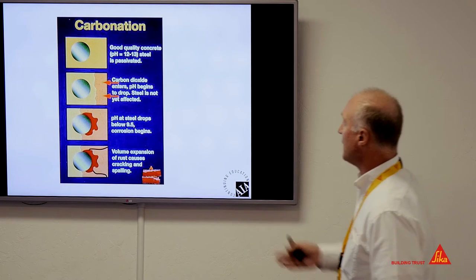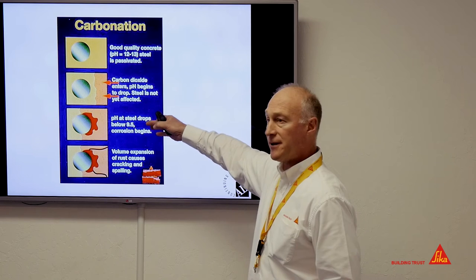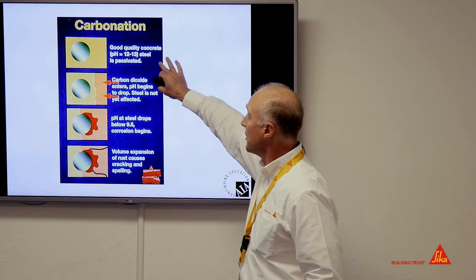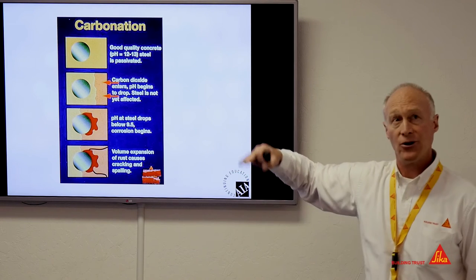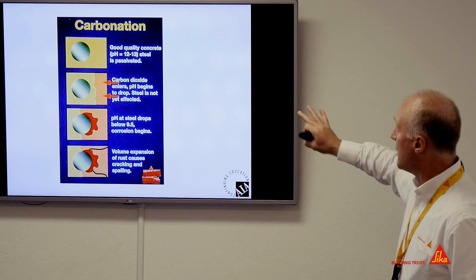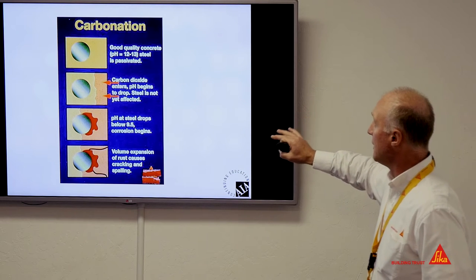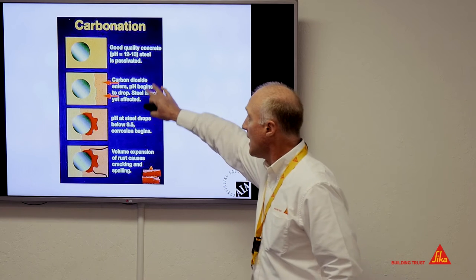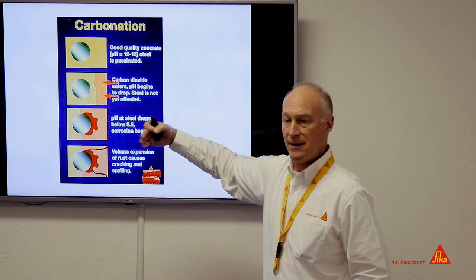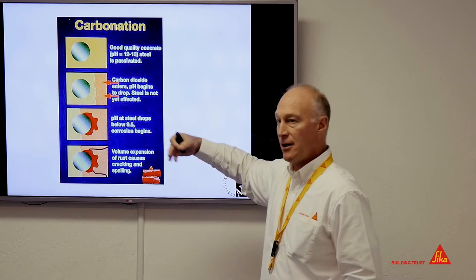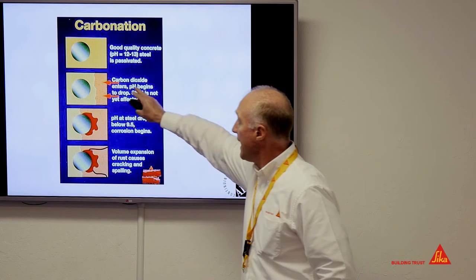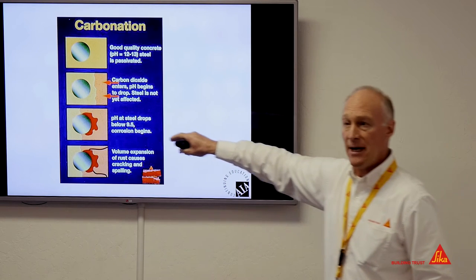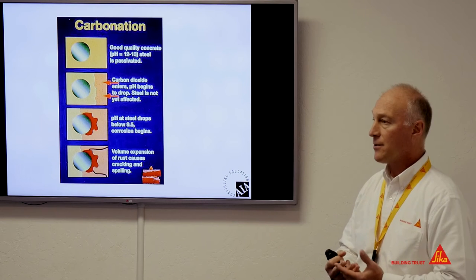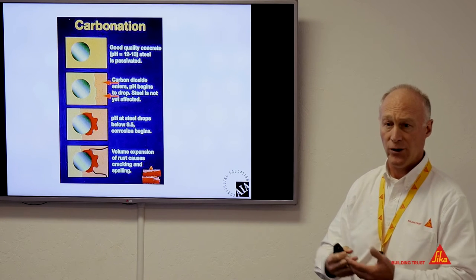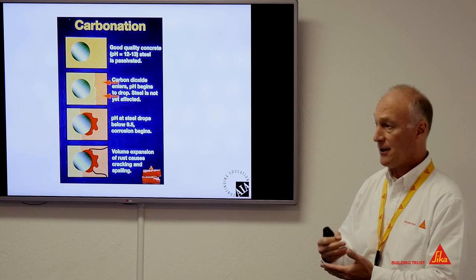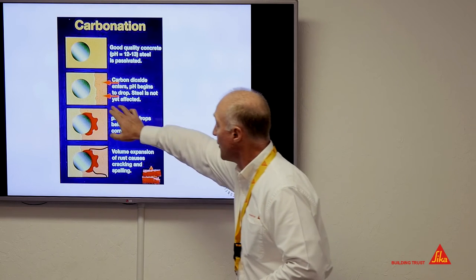Carbonation is a little different. We describe this as a front. So up here is our steel that's been cast in the concrete. It looks good. You're up at around a 12 or 13 pH. The problem is, over time, carbon dioxide that's inherently, naturally in our atmosphere will get into the concrete. It reacts with the free lime of the cement and creates a product called calcium carbonate, which has a lower pH than the concrete itself. And we literally refer to this as a front.